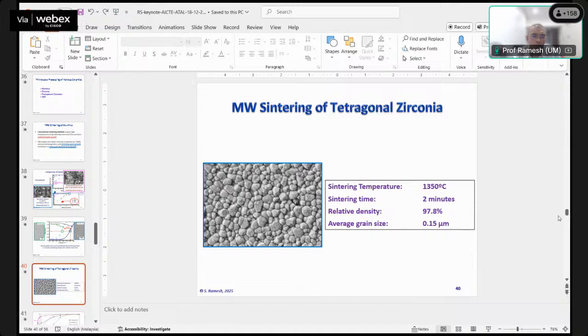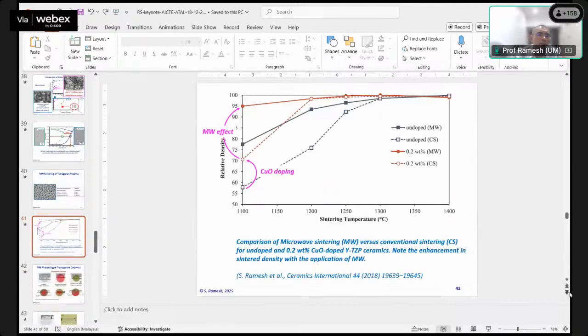Okay. For zirconia as well, we have done a lot of work. You can keep at low temperature for as low as 2 minutes. All right. We are able to obtain 97% dense, 98% dense with an average grain size of about 0.15 microns. So this is another work that I've done using microwave.